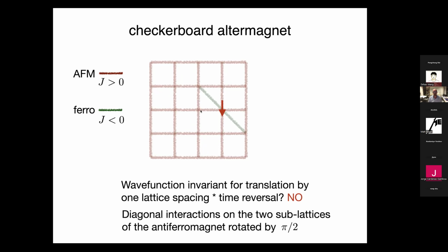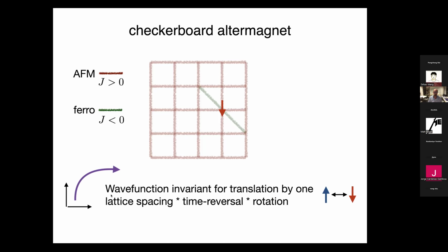If I translate by one lattice spacing and also reverse the spin, do a time reversal operation, then I'll get the down spin sublattice, but these down spins now have an interaction that is along the other diagonal. So this operation, translation by one lattice spacing and time reversal on top of it, does not leave the wave function invariant. The diagonal interactions on the two sublattices of the antiferromagnet are rotated by pi over 2, and I have to account for that in my symmetry considerations. What gives me the invariance is translation by one lattice spacing times time reversal times a rotation, a 90 degree rotation of the lattice, in fact.